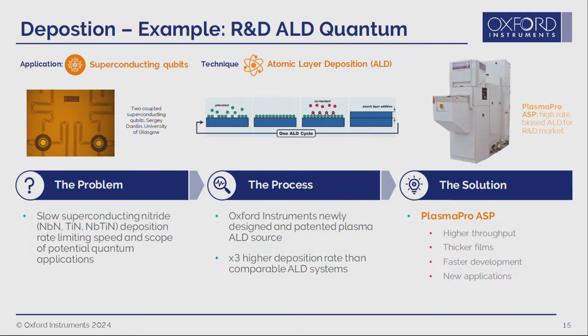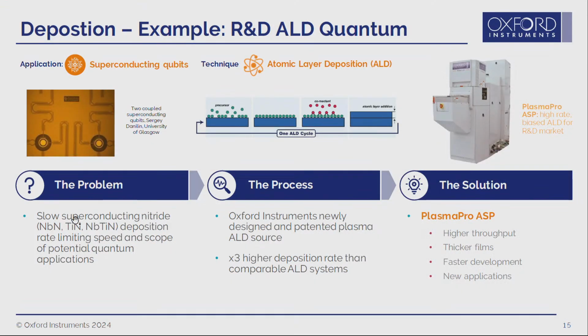One area that we have just looked at for quantum is the deposition of superconducting films, so niobium nitride and titanium nitride. One of the limitations here is that conventionally sputtering is used for these materials, but as device structures change and become higher aspect ratio structures, there's the need for a conformal coating, so atomic layer deposition is used instead. But this is slow, so we've introduced a new piece of equipment for depositing these films much quicker in a conformal manner, so 3 times faster than we currently can for quantum.